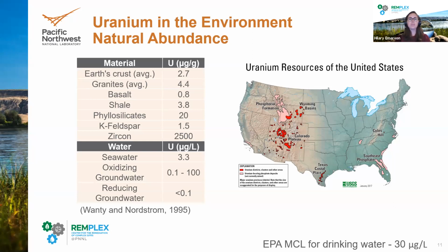per million. And so as another example, if you look at the graph on the right, we have uranium deposits across the US in red, but more importantly, we also have uranium deposits that are associated with phosphate in pink. And so as we talked about uranium complexing strongly with phosphate in solution, it's important to note that we can also form low solubility mineral phases with phosphate.